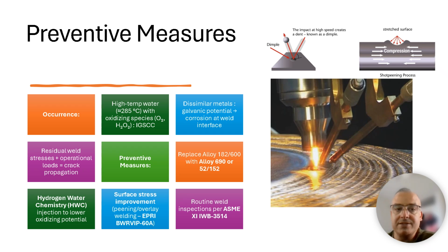To reduce these risks, plants often replace old nickel-based welds with modern alloys like 690 or 52 or 152. They use hydrogen water chemistry to limit oxidizing conditions and apply surface stress techniques such as shot peening or weld overlay. Regular inspections following ASME rules help catch cracks early.